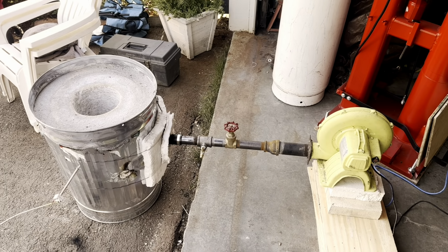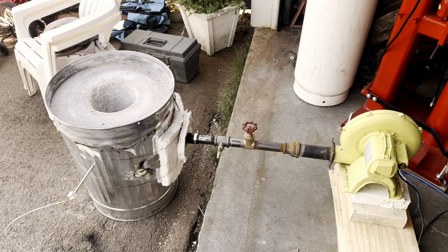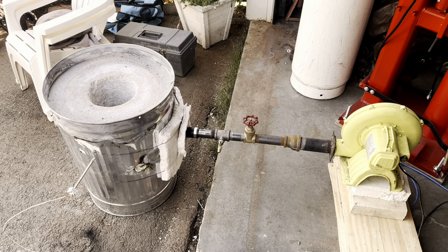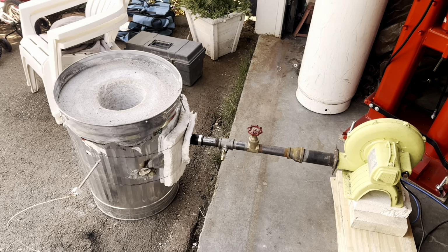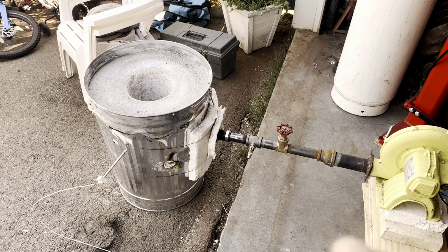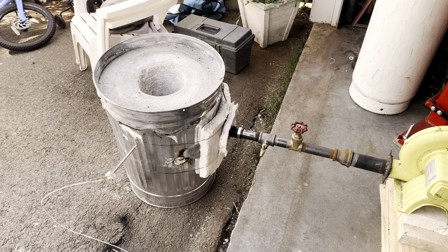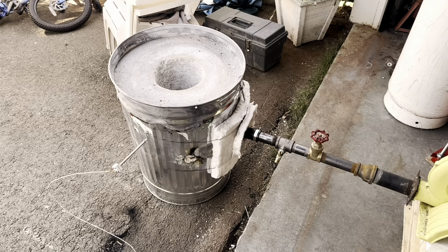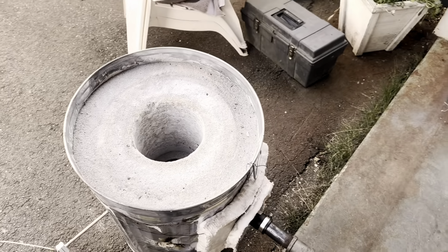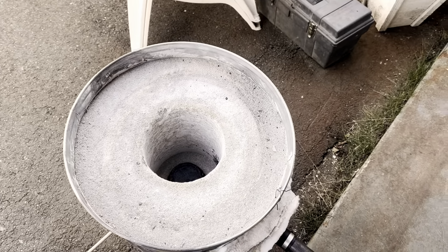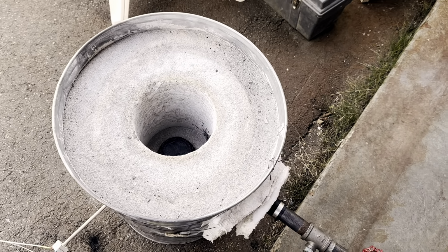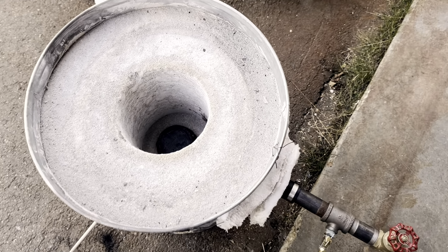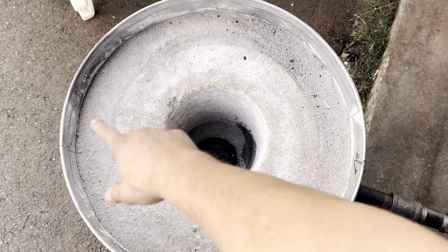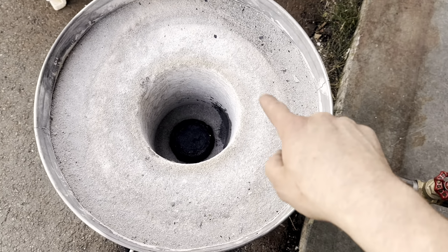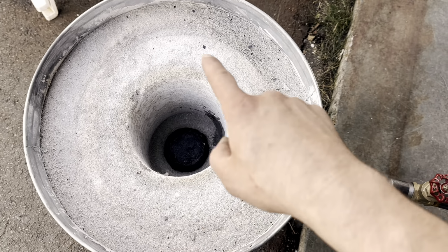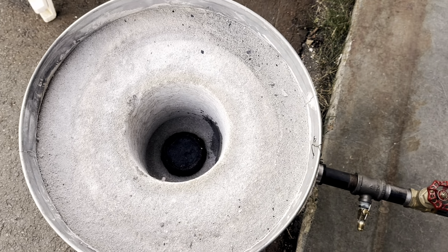Okay, so this is a new furnace design, furnace body and the burner. Trash can furnace, as I like to call it, or furnace to grouch. But I was using this before, and I ended up relining it. And it's essentially 6 inches of Kaowool, and then about 1.5 inches of refractory in the chamber and 2 inches on top. Something I did different too was I casted this whole area. You can kind of see where the lid sits. And before, I only cast it out to the lid. So I like this a little better.